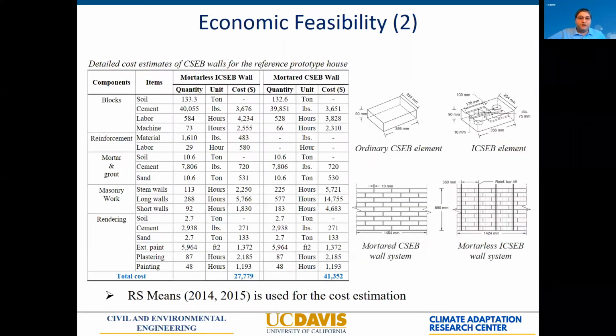Just to explain very briefly what we are doing with these, we are using interlocking blocks with grooves and protruding elements, with also holes to position reinforcement, with the reinforcement that helps in positioning the different blocks and also in providing additional strength. And with this configuration, we were able to reduce by a factor 2 the amount of labor needed for this construction, as you can see here. And that's all you really need in order to make it cost competitive with the wooden housing.